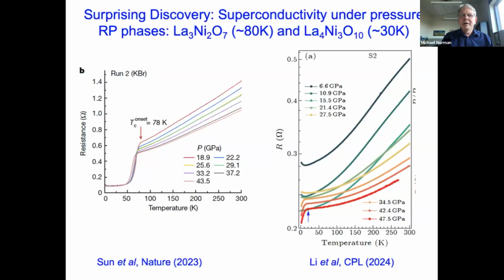for superconductivity. But by putting these under pressure, what's been found in both cases is you suppress the density wave state, and lo and behold, the material becomes superconducting at around 80 Kelvin for 327 and around 30 Kelvin for 4310. Some of the earliest studies show some sort of finite resistance at low temperatures, but as people have made better samples, the low temperature resistivity seems to go to something close to 0 within resolution. So to me, this looks like the real deal.